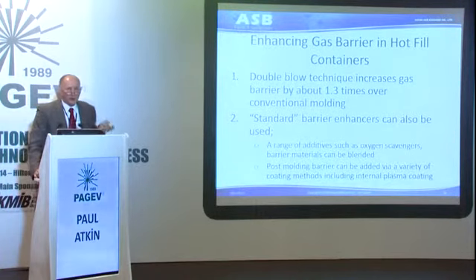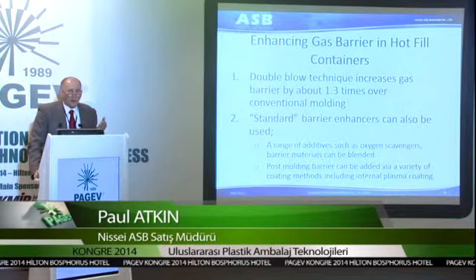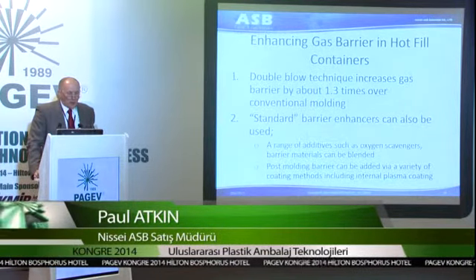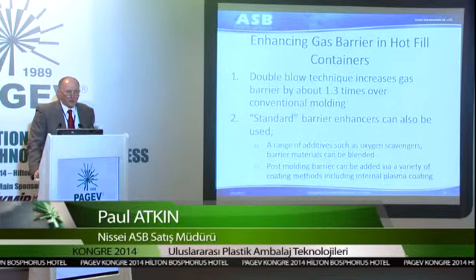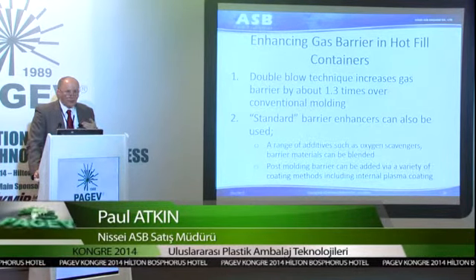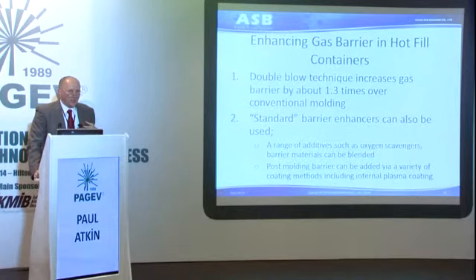Now, gas barrier is always an issue. People want to have oxygen-sensitive products filled, and one of the side effects of the double-blow system is that the natural gas barrier of PET will be increased by around 30%. This often will be enough for the product being filled without any special steps to be taken. But if you have a more sensitive product which needs more oxygen barrier or more moisture barrier, for example, you can use oxygen scavengers or other barrier materials or plasma coating. Anything which is being applied to containers at the moment can also be applied to these hot fill containers.